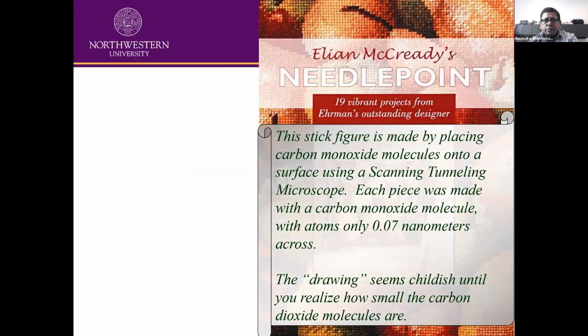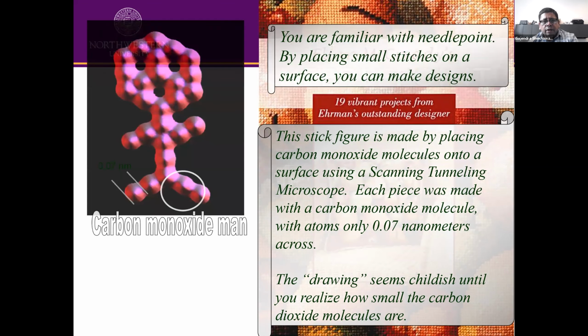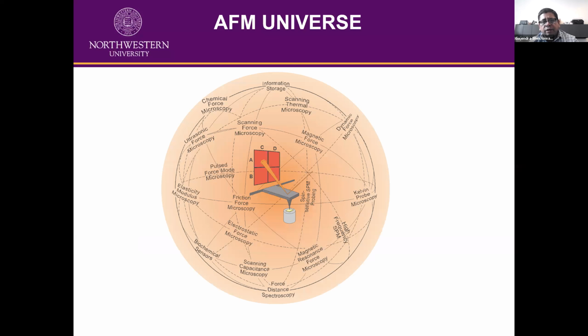When they developed that system, this is how they built the carbon monoxide man. It may not look like much, but at molecular scales they can physically move atoms from the lattice and manipulate them to create these nanostructures. It's like placing carbon onto the surface using a scanning tunneling microscope. It's similar to needlepoint, where by placing small stitches on the surface you can make these designs. So this was the beginning of scanning tunneling microscopes.